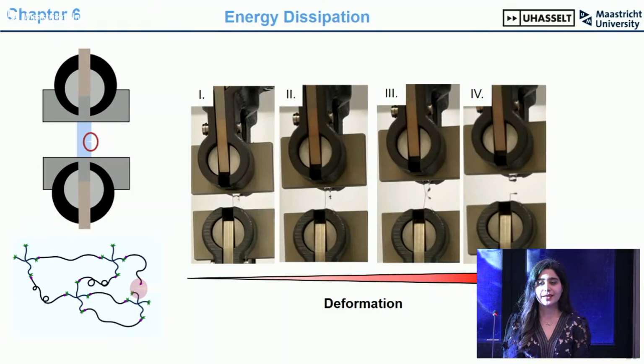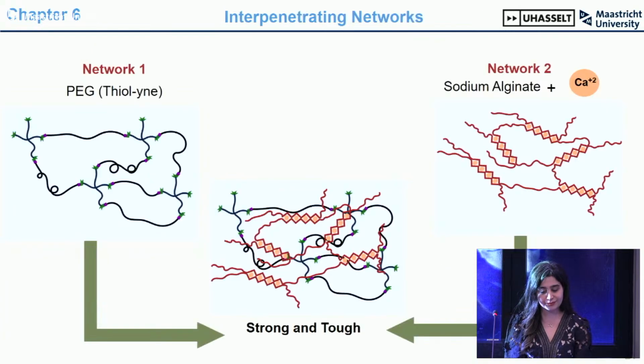As I explained, improving network uniformity and reducing defects can make hydrogels stronger and delay fracture. But these uniform hydrogels don't have a built-in energy dissipation mechanism, meaning that if there's a defect, it can quickly turn into a running crack and rapid failure. A solution to this problem is to add an energy dissipation mechanism by making interpenetrating networks.